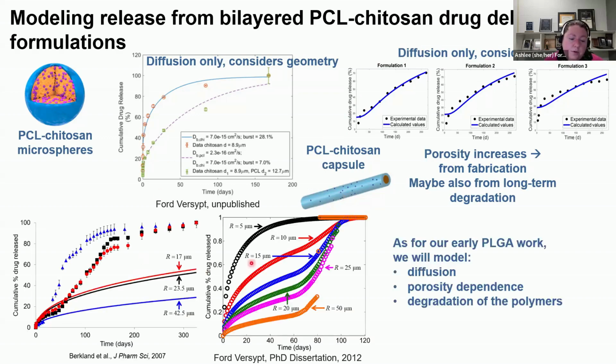And so earlier work that I had done as a PhD student was about degrading polymers that had evolving porosities that were reaction dependent. And so where you could switch from having small particles release their payload faster, when there was a reaction that could change the porosity of the material, that could enable large particles with large porosity to then release their entire payload faster than the smaller particles.